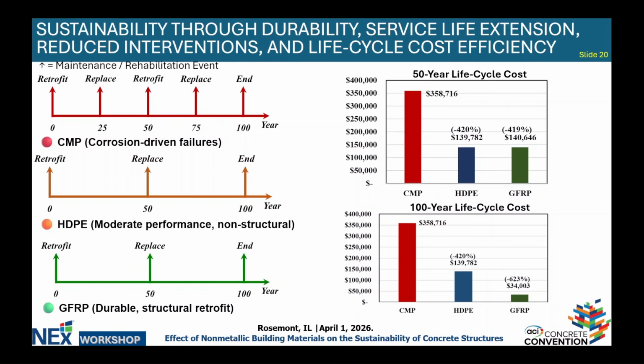GFRP is pretty comparable, but what we've seen in these results is structurally, based on the grout system that is used in the annulus, you have more of a structural contribution from these liners. If you see a 50-year life cycle cost versus a 100-year life cycle cost, yes, initially the cost is high to enable a GFRP slip liner and polymer concrete, but if you look at the 100-year life cycle cost, you have those costs drop down very much for GFRP in comparison to HDPE or CMPs.